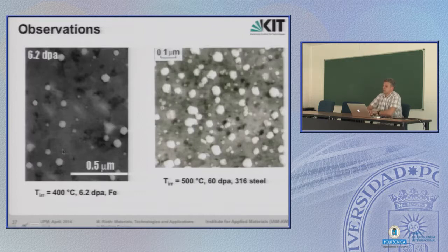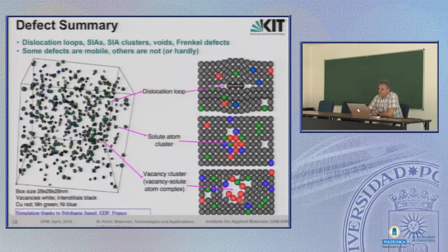Yet another observation. You have to look at the scale here. This is 500 nanometers, this is 100 nanometers, and what we are observing here are missing atoms. So in reality, these are voids, and this is the name of this defect. Single vacancies can cluster, they attract each other, and in the end, what remains is a big hole, or lots of more or less big holes in the lattice. Also, this has, of course, dramatic consequences, as we will see later. So, as a summary, dislocation loops, self-interstitial atoms, self-interstitial clusters, voids, Frenkel defects. These are all typical remainders of an irradiation cascade.